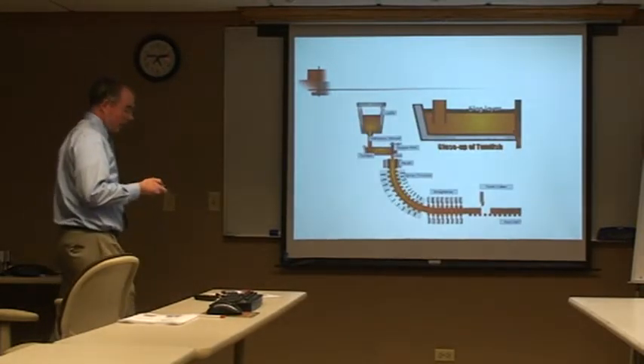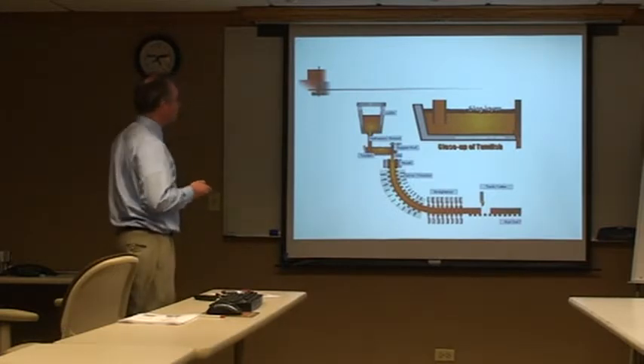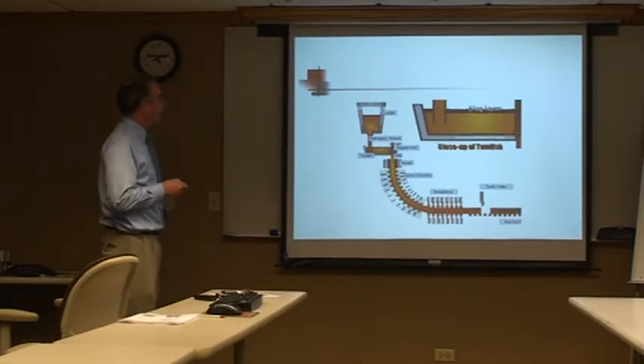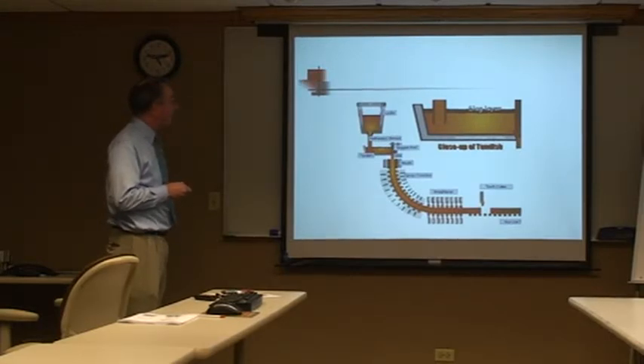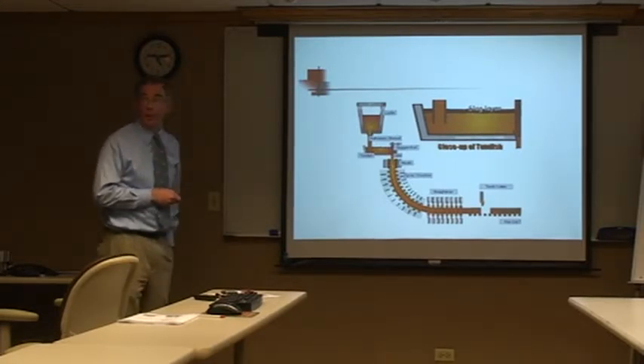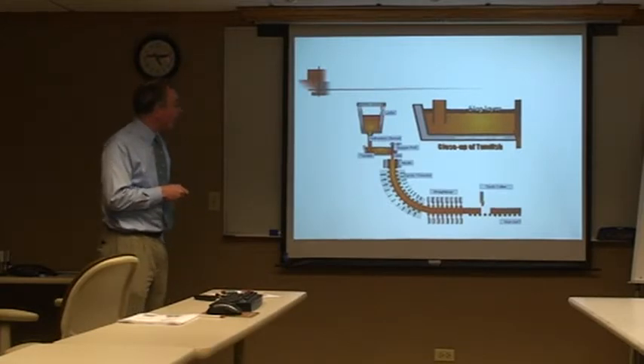Here's a cross-section of what's going on. We have the ladle, and then it's, again, shrouded. Don't want to expose the steel to air. Into the tundish. In this case, this is showing a stopper rod, a way to adjust the pouring rate. Again, we're controlling the pouring rate out of the tundish and into this copper, water-cooled mold.